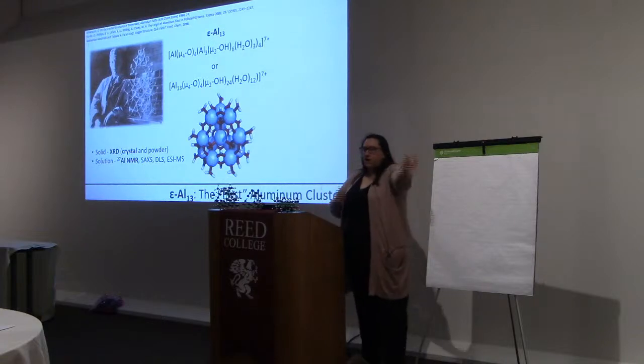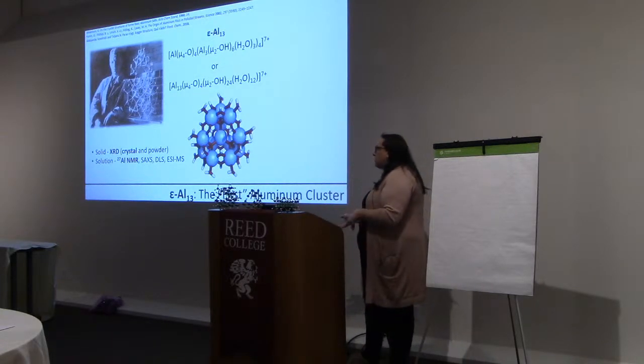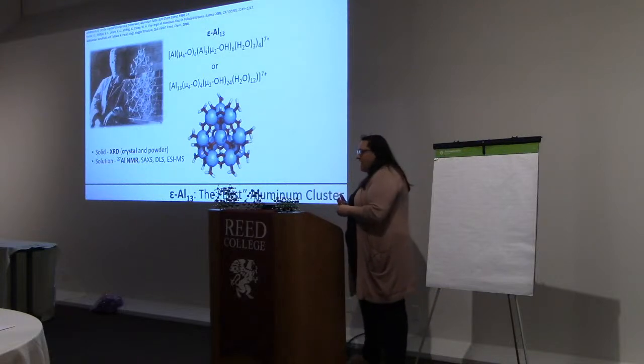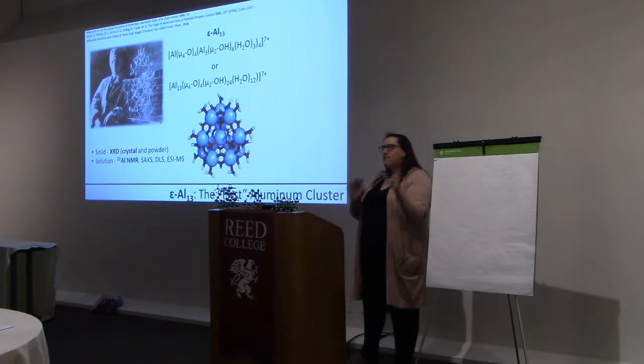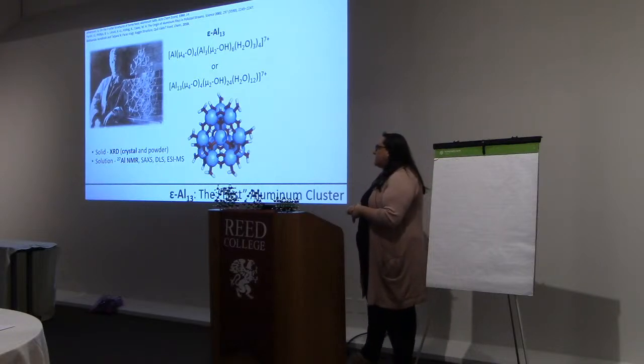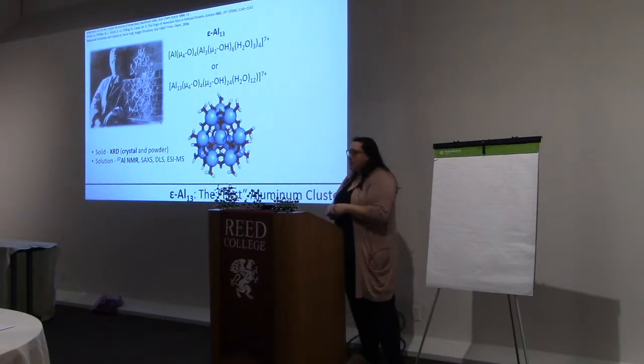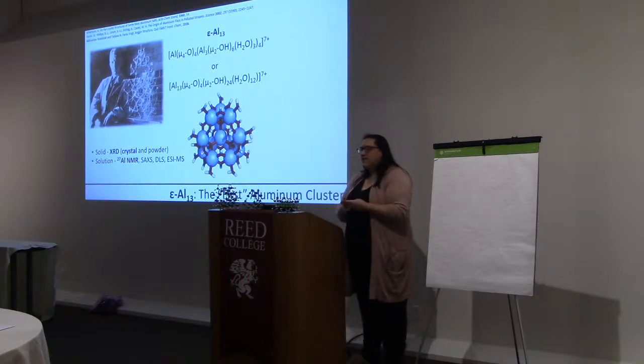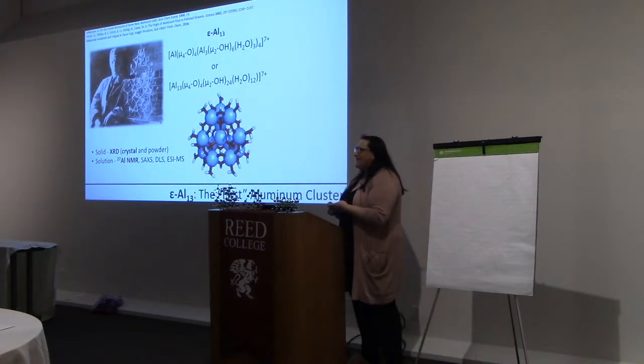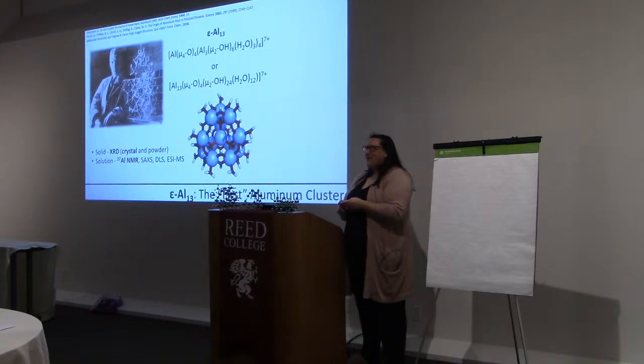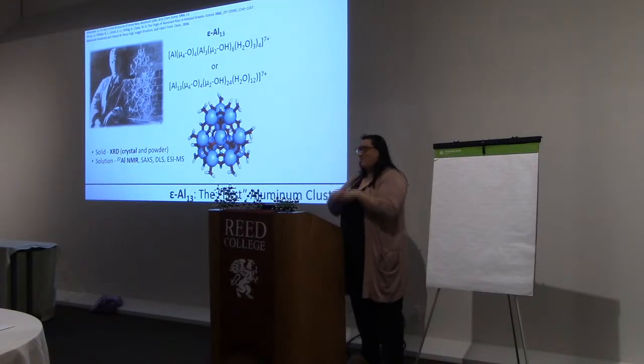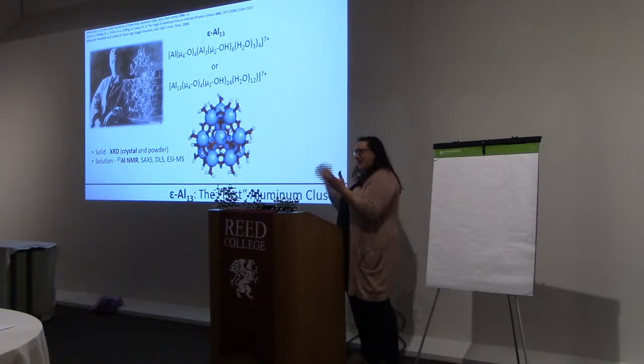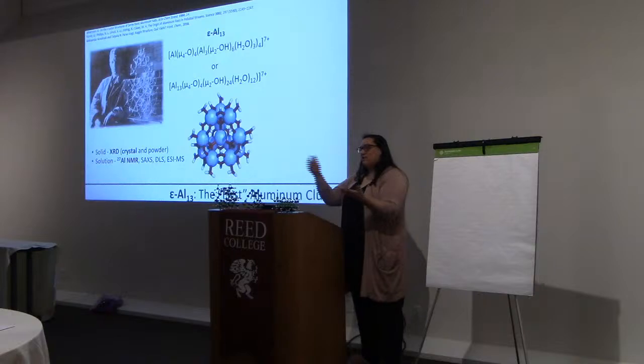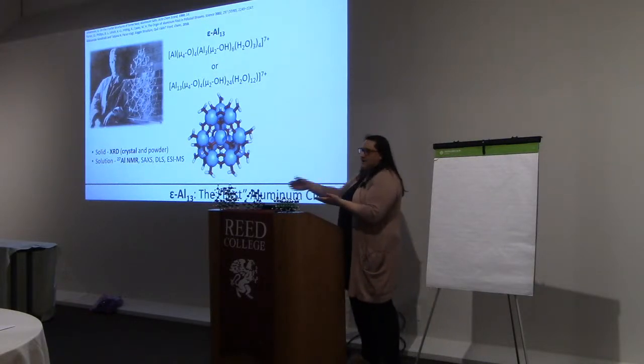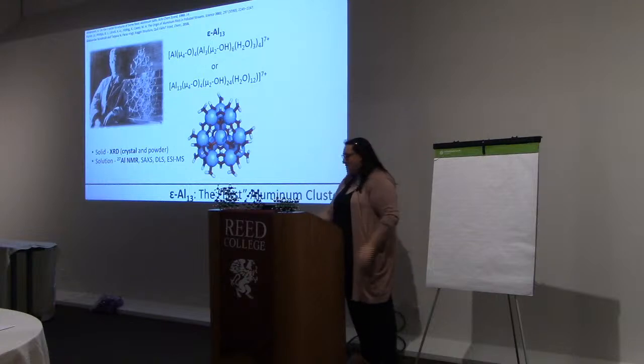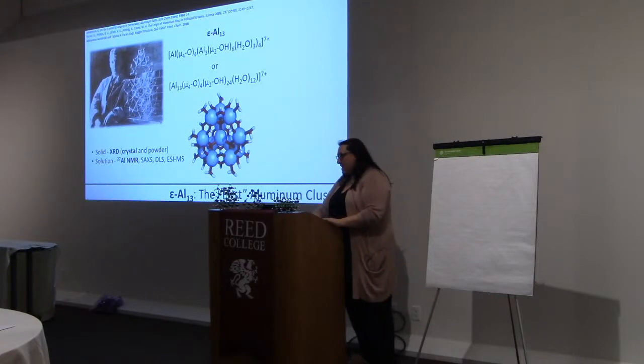This is studied in the solid state using XRD. You can get a single crystal or you can get a powder pattern and tell that you have it. And then in solution, the primary way that people in the literature and historically have studied these is 27Al NMR. But you can use small angle X-ray scattering, you can use DLS, you can use ESI-MS, but there is some controversy about taking a very high charge cluster and blowing that apart in the mass spec and then actually being able to see what was really in your sample versus what you created during that process of analysis. So I would say it's not the best technique, but people in the literature tend to use it sometimes.